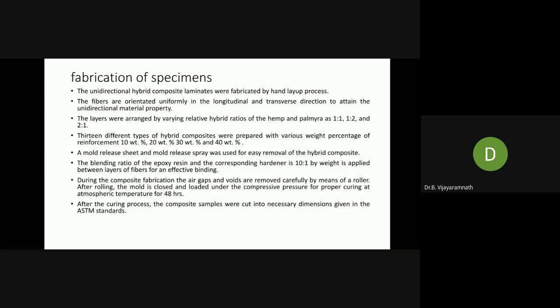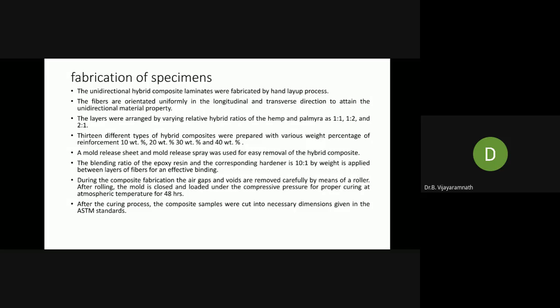Coming to the fabrication of the specimens, we have fabricated 13 specimens, out of which the first specimen is a pure matrix, 100% epoxy, and the remaining 12 specimens are fabricated with relative fiber ratios of 1:1, 1:2, and 2:1 with different weight percentages of 10%, 20%, 30%, and 40%. That is what the total set represents. The curing time we consumed was at most 2 days, that is 48 hours.